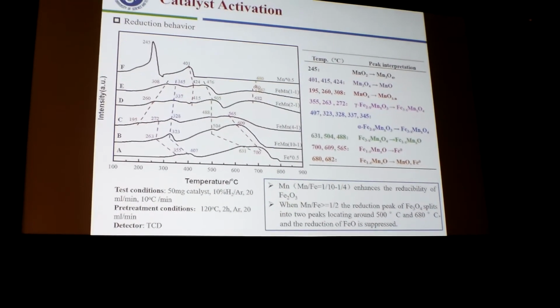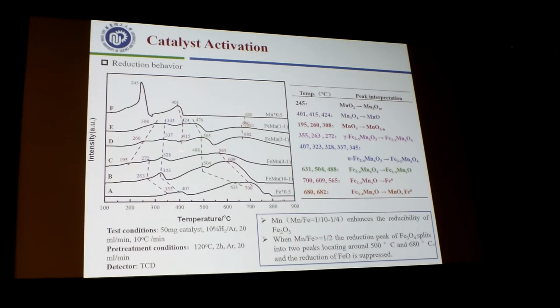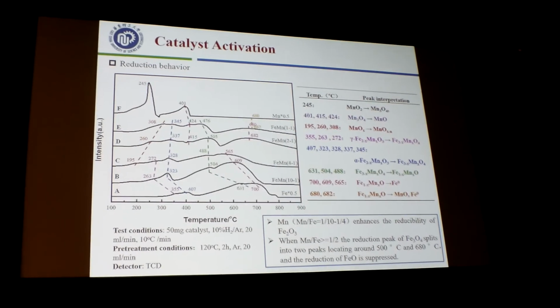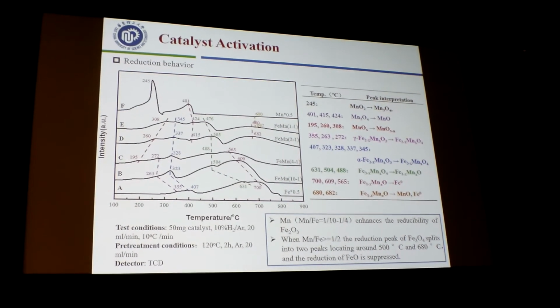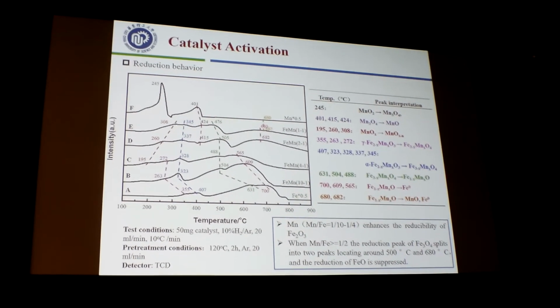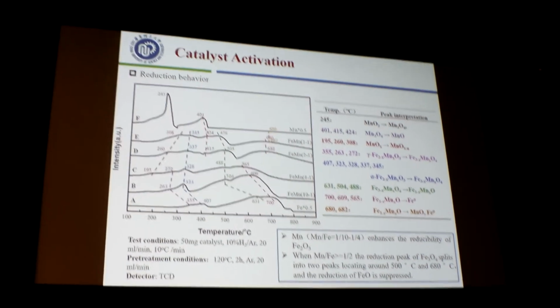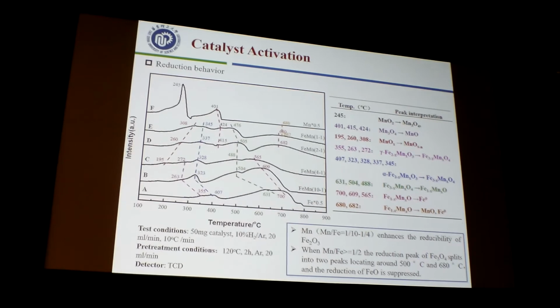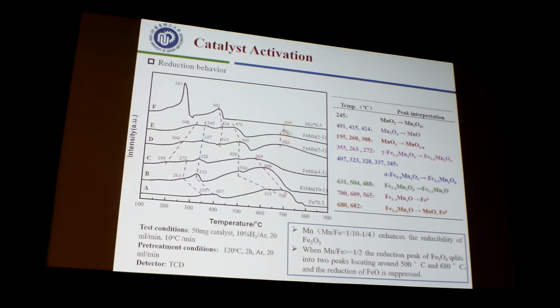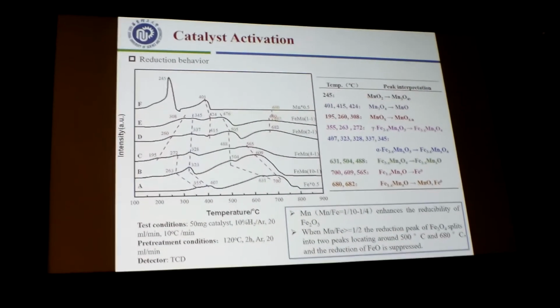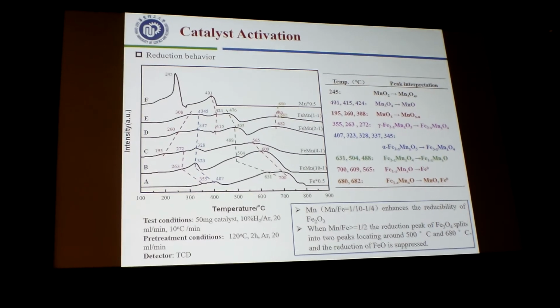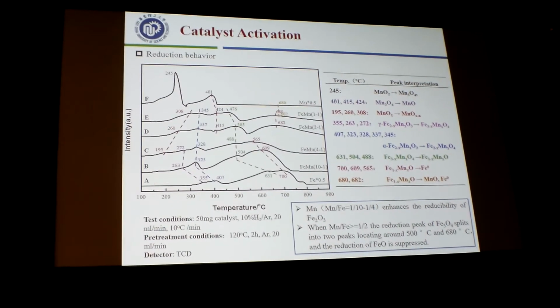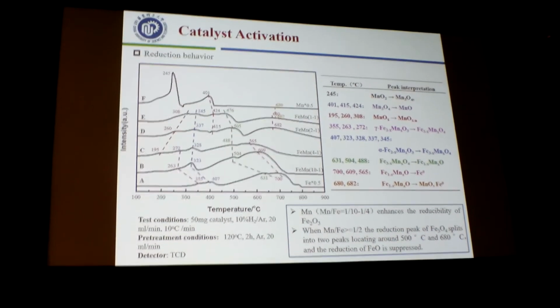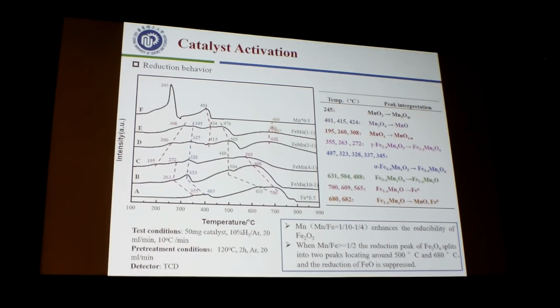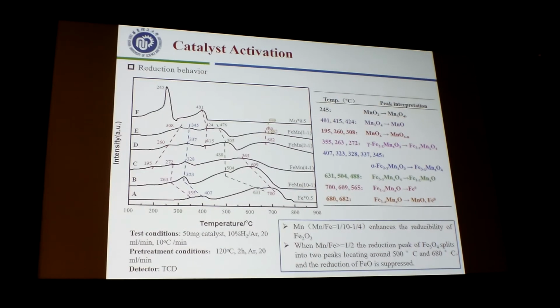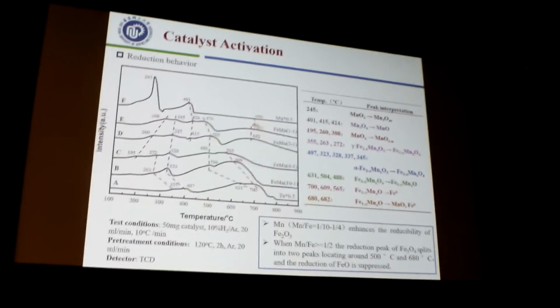And to further investigate the reducibility of the activation, we use the hydrogen TPR. And so we can generally see that the reduction step of the iron catalyst follows the reduction of iron 3 to the magnetite and further to iron O. And as we introduce the manganese to the iron catalyst, the manganese enhances the reducibility of the iron oxides to iron 2, but suppresses the iron 2 to further reduce to the iron metal.